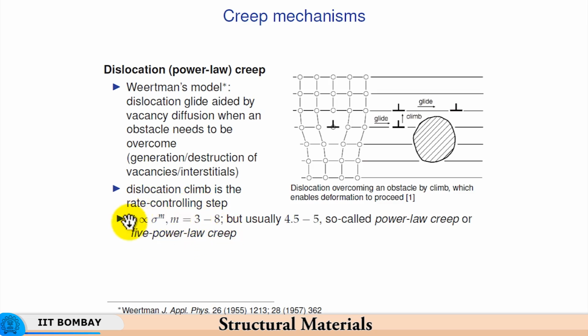Now, because of that the stress becomes a very important parameter, because if the climb is not taking place, then the sensitivity to stress will be higher. But typically for power law creep, because there is also temperature present, 4.5 to 5 is the typical value of m. So, the strain rate dependence on stress is to the extent of power of 4.5 to 5.